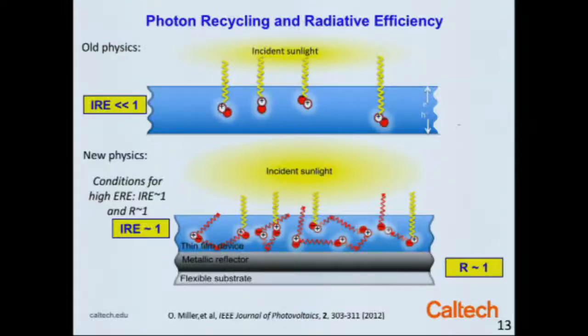What that means is that we can have more than 100 luminescence recycling events where carriers recombine, re-emit photons inside the material, recombine, re-emit, recombine, re-emit, more than 100 times. What that means is that you end up with a very dense gas of photons and electrons here due to this recycling process, relative to this process where the radiative efficiency is not high.